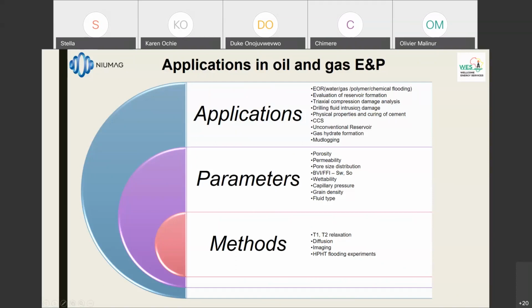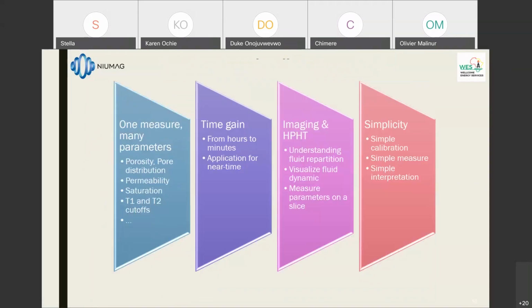damage analysis to see if there is a decrease in the porosity under certain conditions. Drilling fluid intrusion damage, physical property and curing of cement, conventional carbon capture and storage, unconventional reservoir, gas hydrate, and mudlogging. Okay, there might be other applications. So the big advantage: one measure, many parameters, the time gain. We move from hours to minutes, and the application is almost near real time for cuttings, for example.